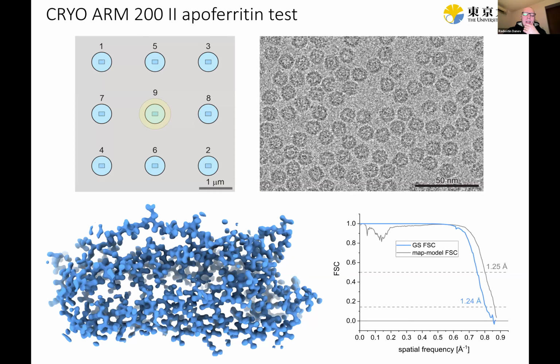In the end, I wanted to collect at 600,000, but there was such a big shift that I couldn't make the experiment work. So I used 500,000, one magnification lower. It was just such small practical details which made things more difficult. And this data set, because this was maybe a few days before the camera had to be mounted, already had some parasitic remaining beam tilt, about 1 millirad, which is compensated in software, but it's better not to have it there.